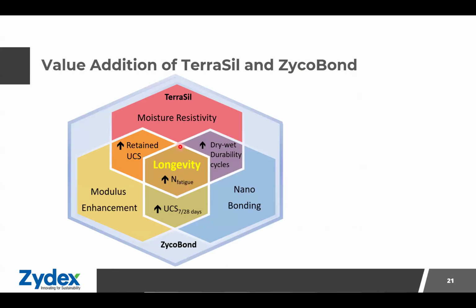Now, what is the value addition that these chemicals are adding? We have two chemicals that go in conjunction. The first one is Terrasil and the next one is Zycobond. Terrasil essentially gives the water resistivity, while the Zycobond gives the modulus enhancement and nanobonding. So the combination of water resistivity and modulus enhancement gives the higher retained UCS. The combination of moisture resistivity and nanobonding gives the higher dry-wet durability cycles, whereas the combination of modulus enhancement and nanobonding gives the higher UCS, either at 7 or 28 days.